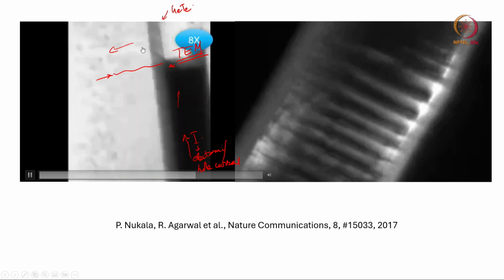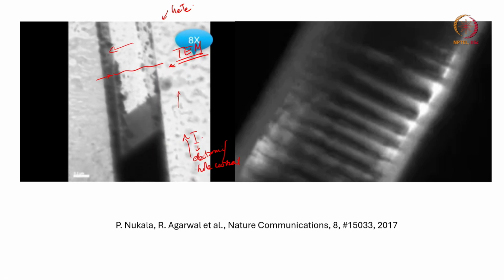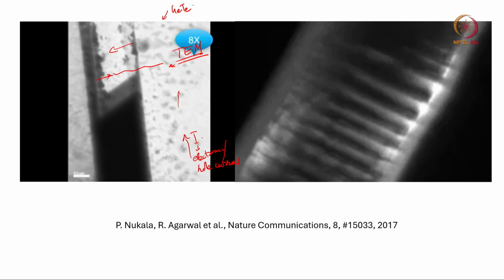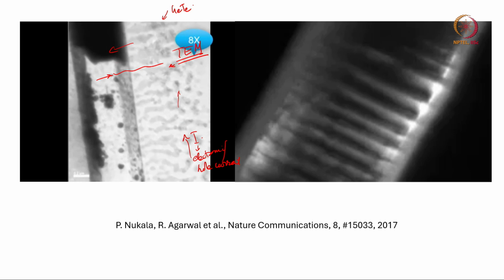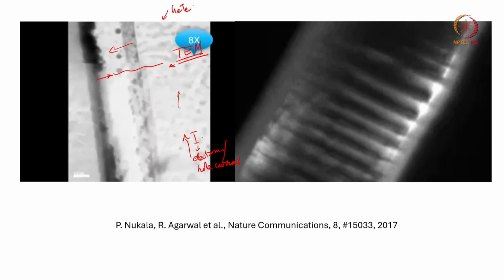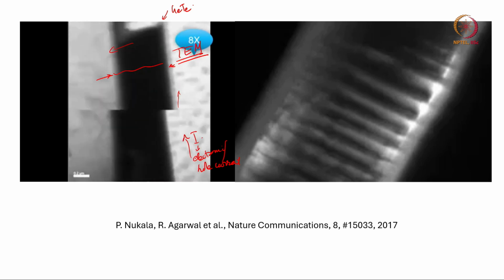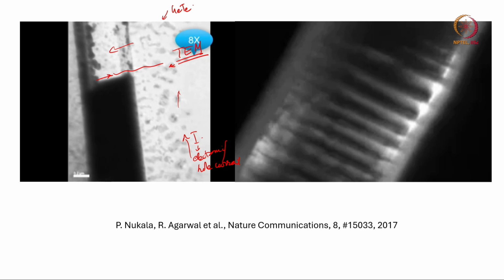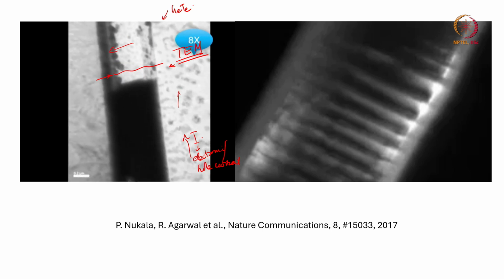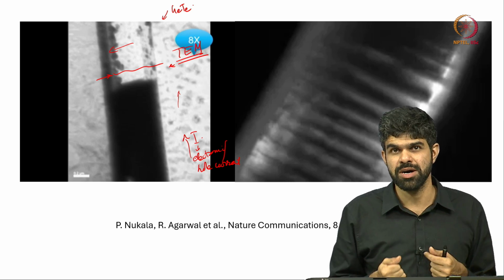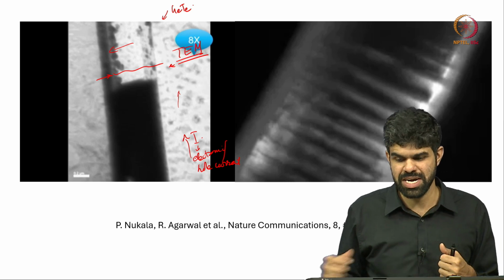So part of it melts and escapes, and so the rest of it just flows on this side and that side. Okay. So this is electromigration in an exaggerated way. So this is not just that I am also heating the nanowire, right. So it is not just that I have an electron wind force that is moving the atoms, it is also heating the lattice, and still the atomic motion becomes more pronounced in that fashion, right.